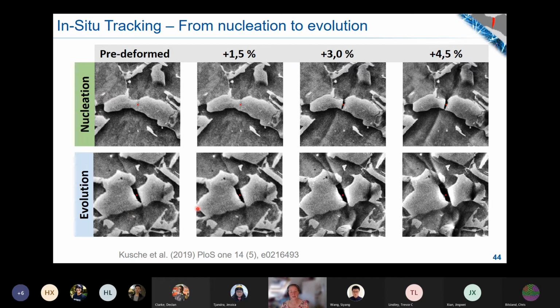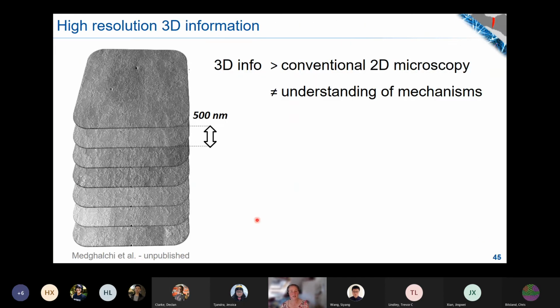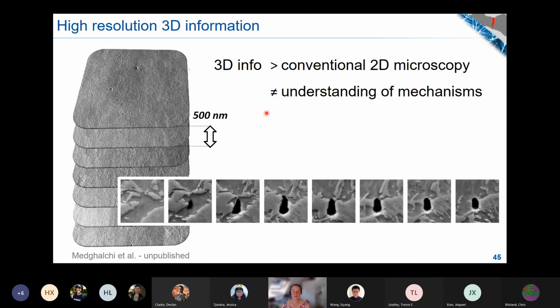So we think that now that the analysis is automated to a large extent, we can actually go into 3D. So we're now starting to polish our materials and take high resolution, large area maps in each section so that we then get a rich 3D data set. And we already know that this will give us new insights. For example, that the classes we tend to look at, which we just took from the literature and what we do normally, might not be all that meaningful. It's not that surprising, but it's nice to have confirmation.